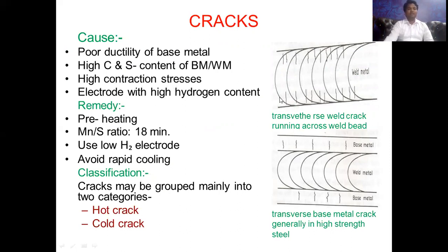Remedy. The remedy is that preheating of the material must be carried out to avoid the cracks. Manganese and sulfur ratios should be minimum. Use a low hydrogen electrode. Avoid rapid cooling. Rapid cooling of the material has to be avoided in order to avoid cracks.